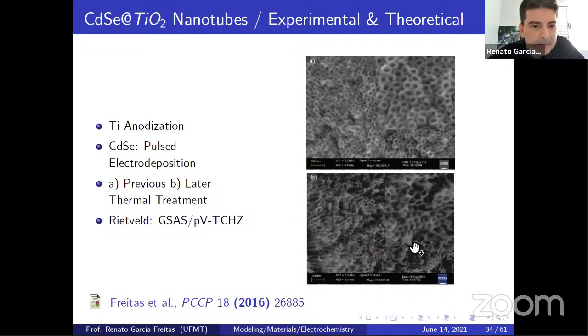In this paper, we again made titanium anodization, obtained titanium nanotubes, and electrodeposited cadmium selenide, because the bands of cadmium selenide are quite different. For titanium nanotubes, as all of us know, the band gap is almost 3.2, isn't it? But cadmium selenide is quite shorter. So we have a very special band gap and band position, like this one. The intent was that the cadmium selenide absorbs the species and injects directly into the conduction band of titanium oxide.